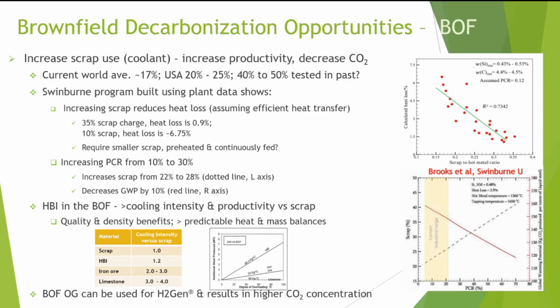Also, the HBI in the BOF has a greater cooling intensity than scrap does, and of course, it increases productivity. And the charts at the bottom just reiterate that. The thing to note here is that the H2 gen, if they take the off gas from the BOF, actually get a higher CO2 concentration also for use later.